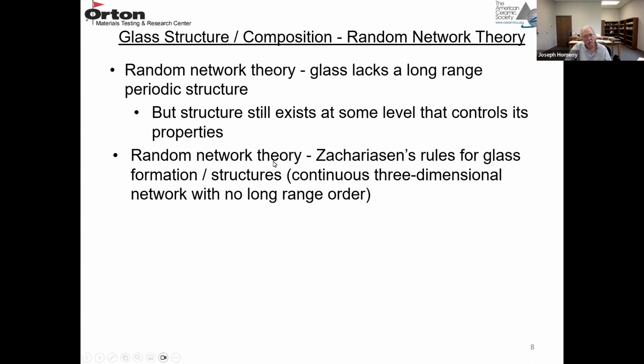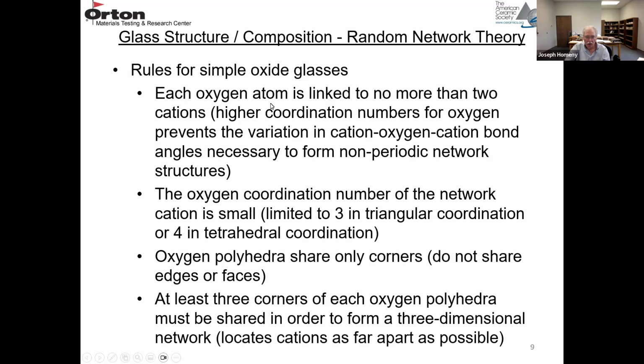So the random network theory, there was a person named Zachariasen. He developed a set of rules for glass formation and glass structures. So his rules give a continuous three-dimensional network with no long-range order. So I have the rules listed here for a simple oxide glass. So each oxygen atom is linked to no more than two cations. So this is that typical tetrahedron unit with four oxygens and silicon at the center.